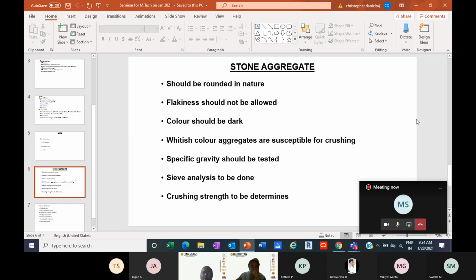The darker the aggregate, the stronger it is, because whitish color aggregate will not have the strength of a dark stone aggregate. Whitish color aggregates are susceptible to crushing. The crushing strength of the white aggregate is very low. That's why the color should be dark. Specific gravity of the aggregate should be tested. Here again, the sieve analysis is very important. That also has to be tested, and crushing strength has to be determined. Again, all the test results should be entered in the test register.